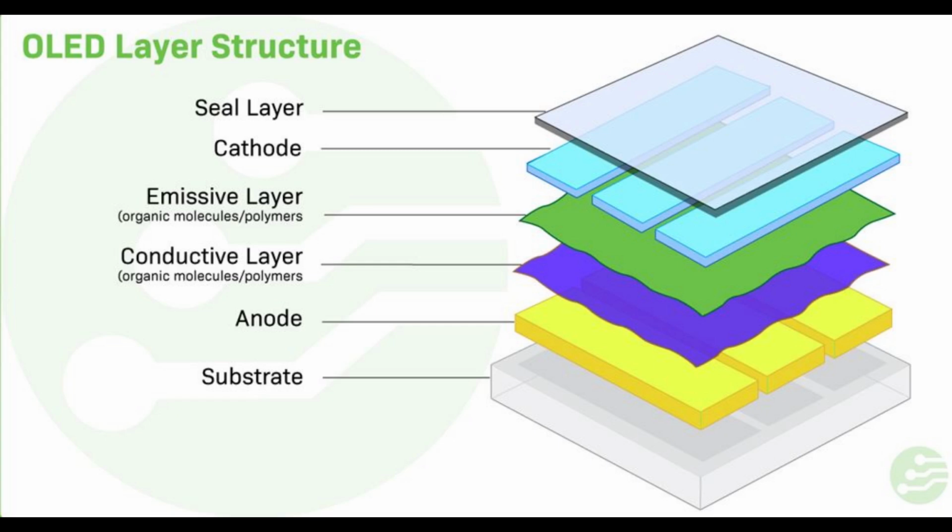PHOLEDs can be deposited using vacuum deposition through a shadow mask. Typically, a polymer such as poly(N-vinylcarbazole) is used as a host material to which an organometallic complex is added as a dopant. Iridium complexes such as Ir(mppy)3, as of 2004, were a focus of research, although complexes based on other heavy metals such as platinum have also been used.